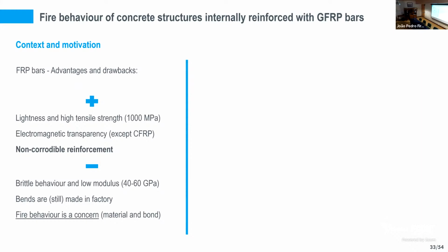So the advantages of these technologies are very well known. These FRP bars are very light. They present a very high strength, but the main advantage is that they do not corrode. However, they present a brittle behavior. The elastic modulus, especially when we are dealing with GFRP, so glass fiber reinforced polymer bars, is relatively low when compared to conventional steel. Bends are possible, but they are still made in the factory.